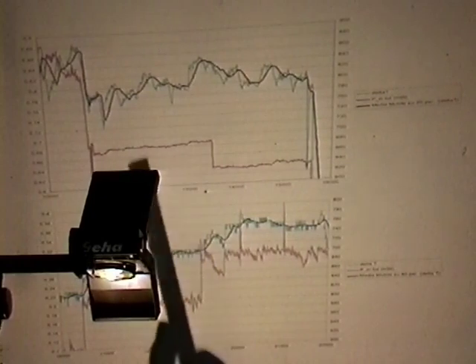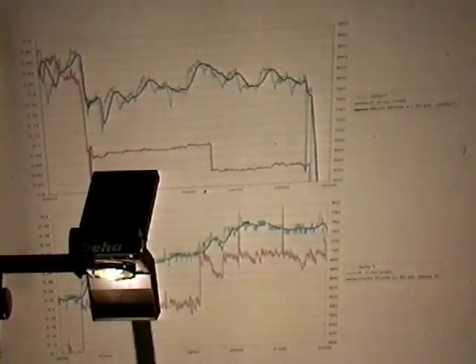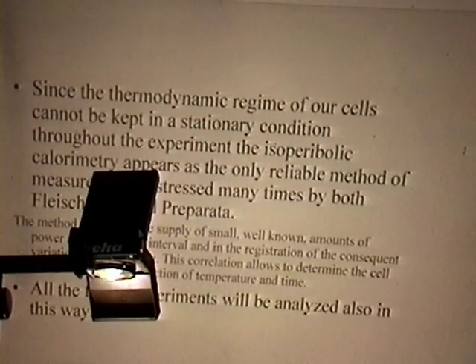Here is the response of the temperature. This is the behavior of the temperature inside the cell compared to the reference external temperature. You can see here that even if the input power is quite the same, the response of the system is qualitatively different. This is a very noisy signal. This is a very smooth signal. What does it mean? It means that the thermodynamic regime of our cells is not in a stationary condition during all the experiment. It's impossible. If there is some heat production inside the cell, there is a change in the thermodynamic regime. So, by definition, it's impossible that our cells work in a stationary condition.